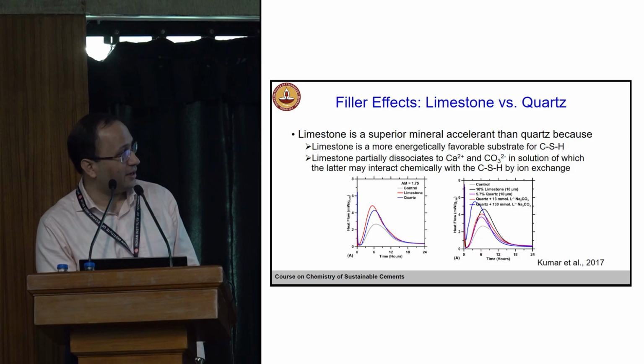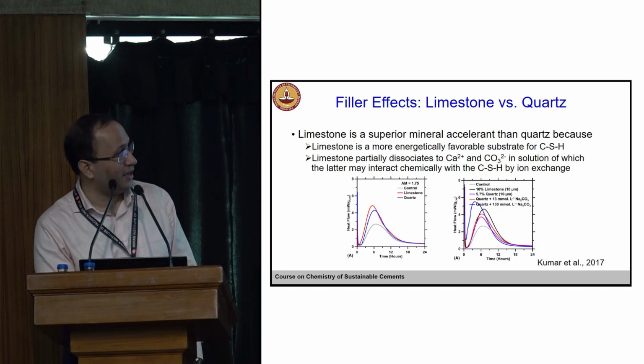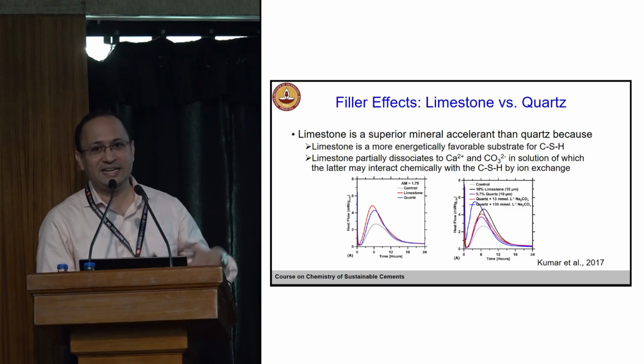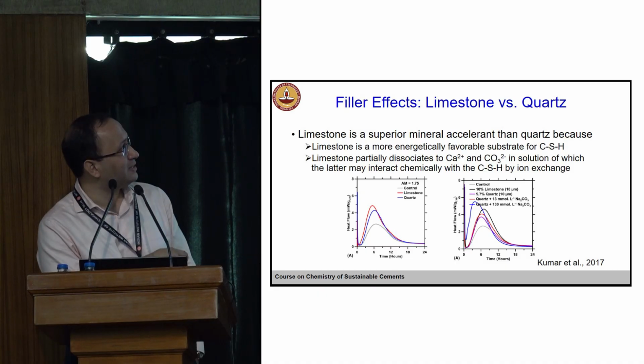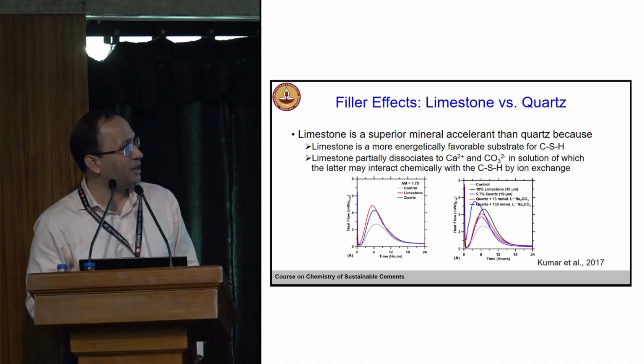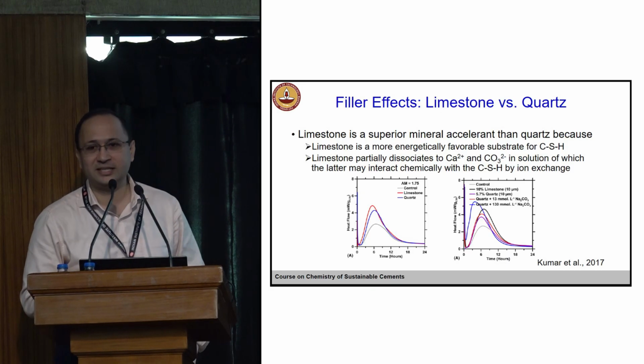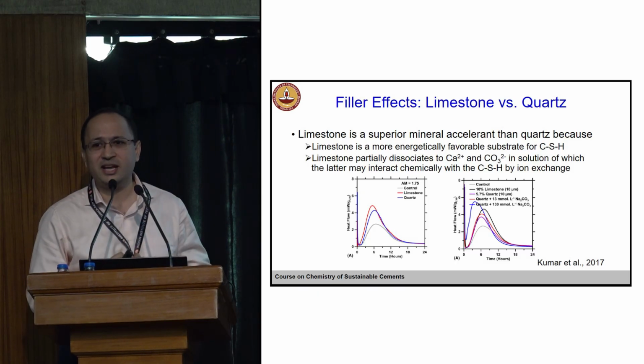It's interesting. In this study, what they looked at is that even with quartz, if you add extra carbonates, you can boost up, you can increase the heat flow. So basically what it comes down to is that the limestone partially dissociates to calcium and carbonate ions in solution, which may later react chemically with CSH phases. So it has some additional benefits. The chemistry is such that there are some differences compared to a non-inert material.